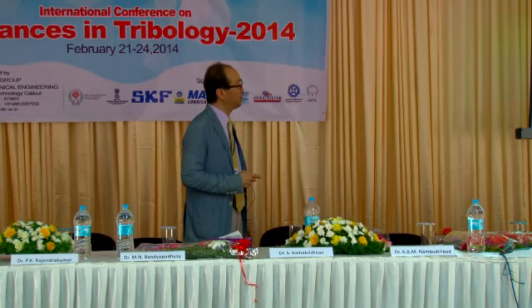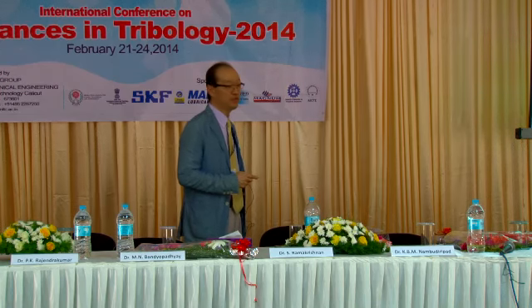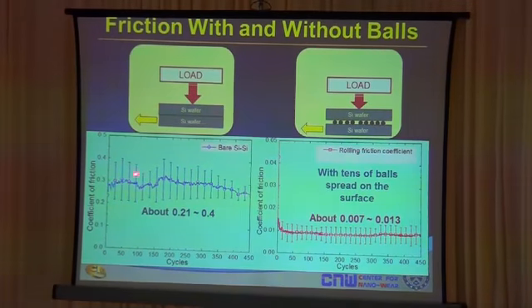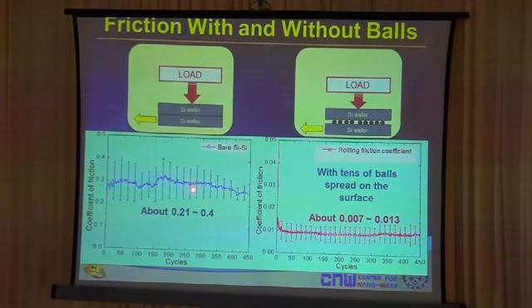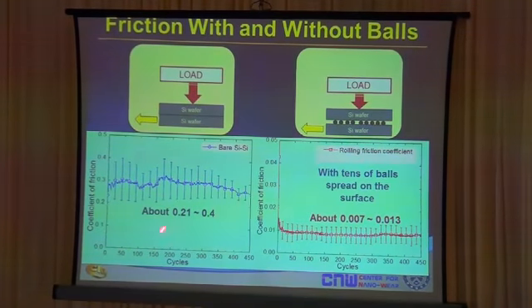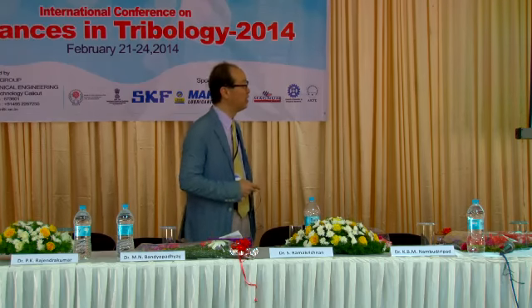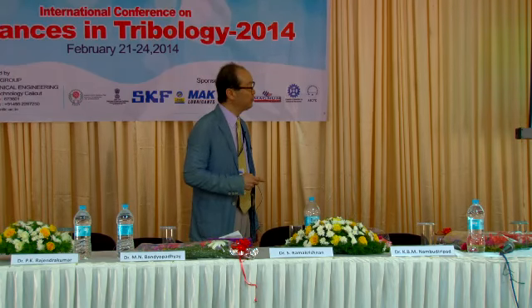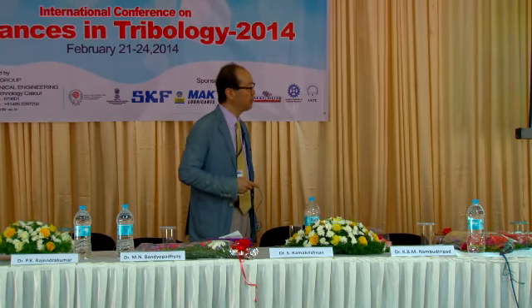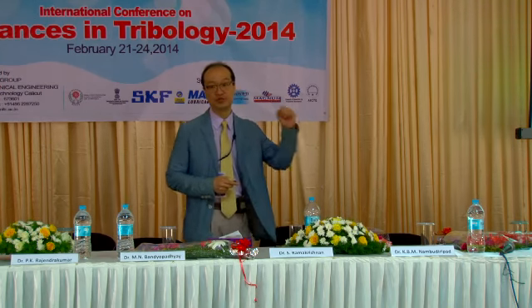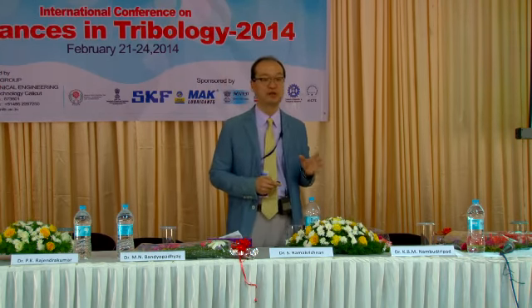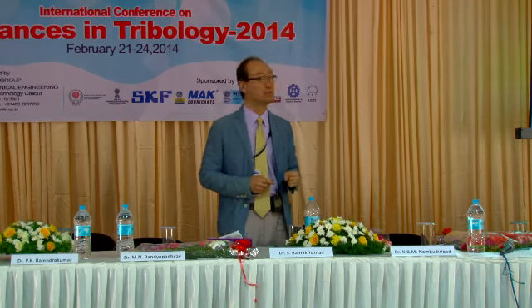Now, without the balls, between silicon and silicon wafer, obviously the friction would be high and very unstable. So you have a very large standard deviation in the frictional force, and the friction coefficient is about 0.2 to about 0.4. With ball bearings at the interface, they're effective in reducing the coefficient down to about 0.007 range. In other words, these micro ball bearings do work.